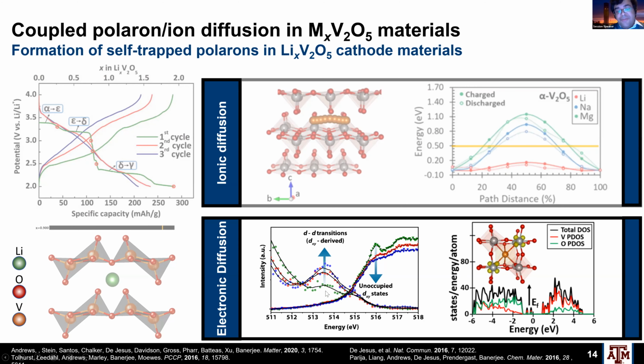And as distinctive evidence for small polaron formation, we've studied this a fair bit. We saw some signatures of small polaron formation that I'm going to show you in a few seconds in X-ray absorption spectra. We saw the Pauli blocking of dxy states, but this right here is some beautiful RIXS data where we can see the dxy-derived polaronic states increase in intensity, and the X-ray absorption spectra show that the unoccupied dxy states are decreased in intensity. So some really smoking guns for this dxy polaron being formed in V2O5.